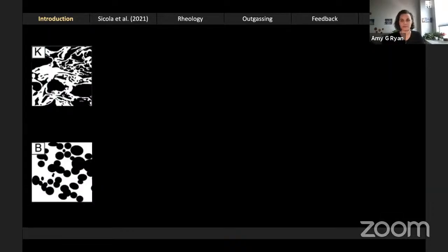So let's take 2 extremes. The top one here represents volcanic melt particles that have begun to sinter together, but host abundant intergranular space. And you can visually assess that the intergranular space here is quite well connected. In contrast, the image on the bottom here represents a melt that is vesiculated, so grown its own bubbles. And while those bubbles may communicate with 1 or 2 other bubbles around them, overall the connectivity of the pore spaces is quite low.